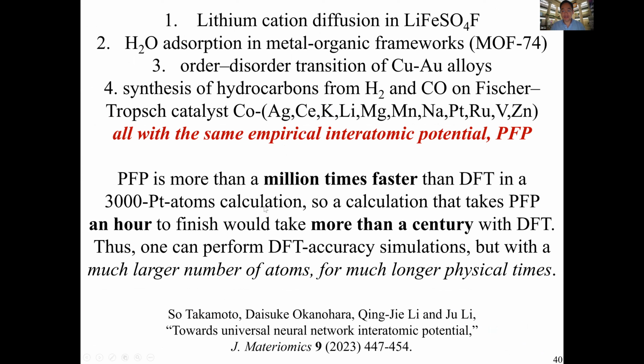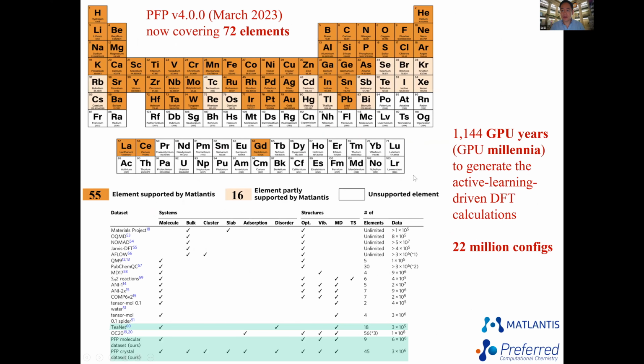The computational efficiency is like this. So if we do 3,000 platinum atoms, which is just like a 4 nanometer, 5 nanometer cluster of platinum, then with DFT, it would take a century if you do the standard plane wave DFT. But with PFP, it would just take an hour of computation. And the newest version 4 release is now covering 72 elements. And I've been asking them to do the actinides as well, because I'm in nuclear engineering and we care very much about actinides. So it's going to happen.